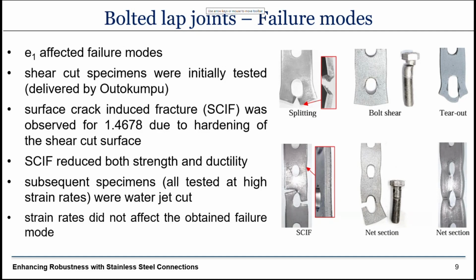But for the novel material, the 1.4678, for the shear cut specimens, that's what we got. And that was also accompanied by a pronounced decrease in ultimate stress. So we got a tensile failure about 15% lower than the one we got for the water jet cut specimens. And that's also one of the reasons why we ended up doing more tests, because then we had to order additional specimens that were water jet cut.